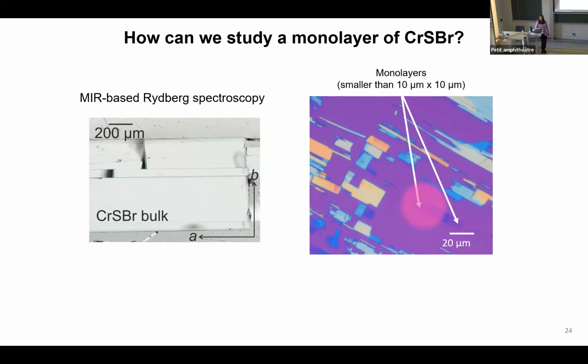So the signal that I will acquire will be heavily affected by the neighboring flakes, and it will be buried in the background. So our trick to bypass this diffraction limit is going to be using ultra-fast terahertz polarization nanoscopy technique. I will show it to you shortly.